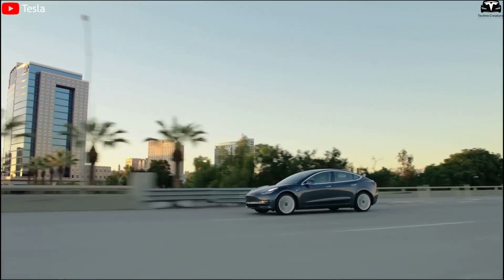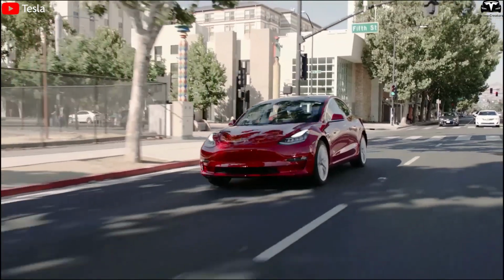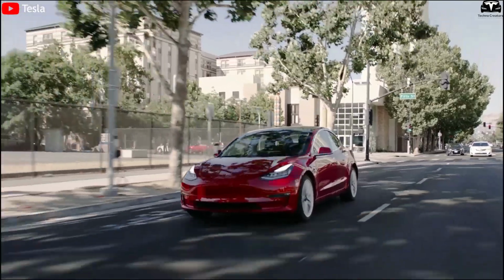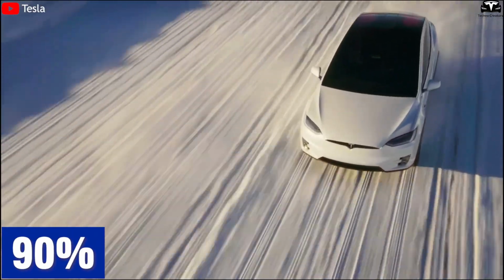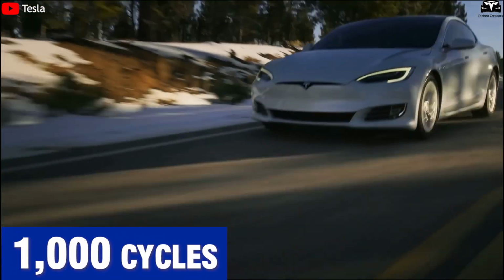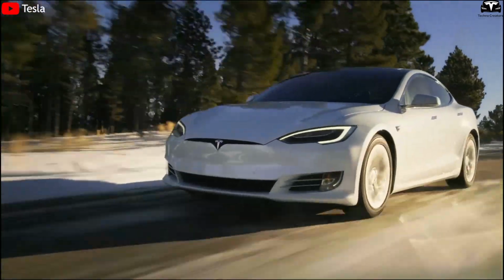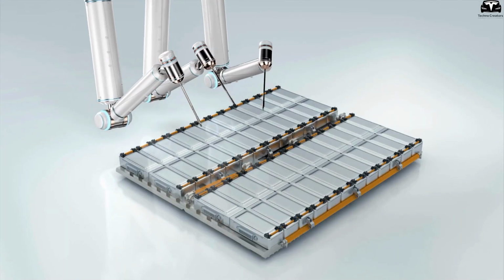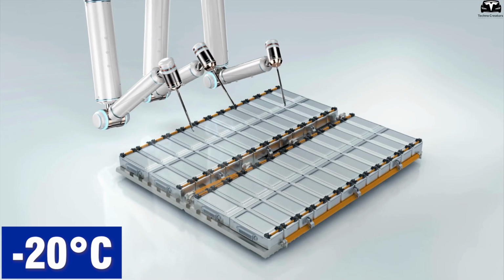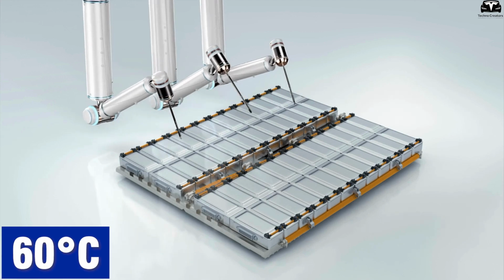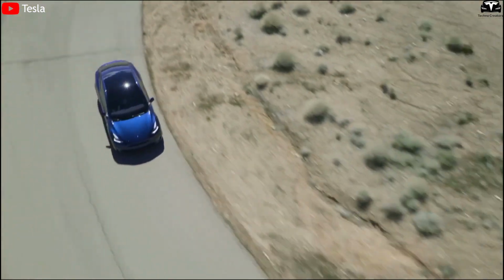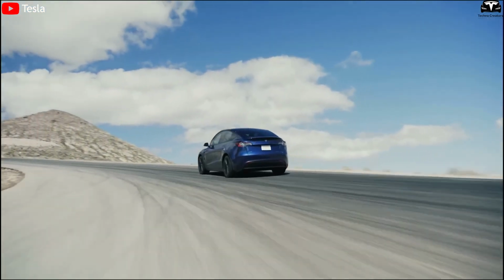Compatibility between electrolyte and electrode materials is also carefully studied to minimize side reactions, maintaining over 90% efficiency after 1,000 charge-discharge cycles. Electric vehicle batteries typically operate across a temperature range from -20 degrees Celsius to 60 degrees Celsius, enduring vibrations and shocks during use.